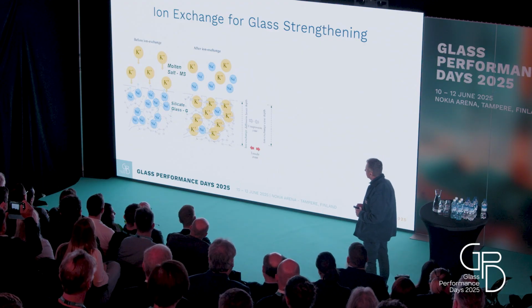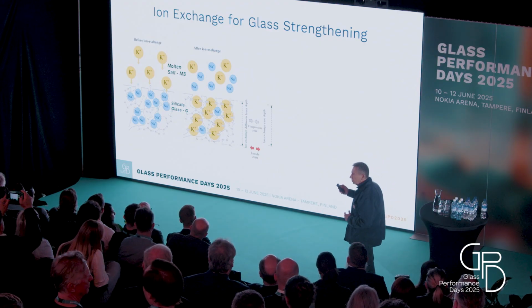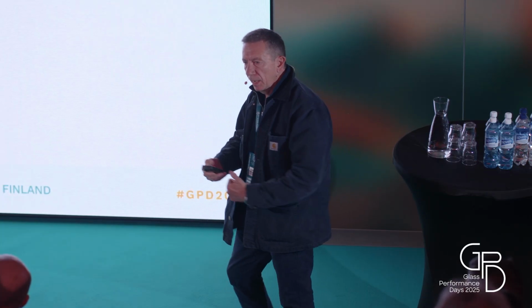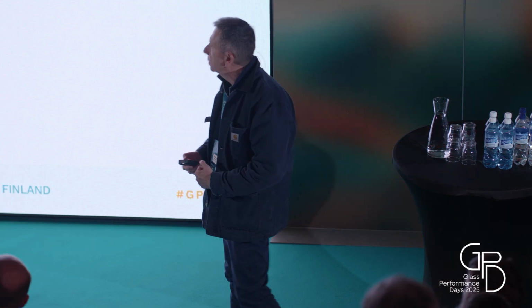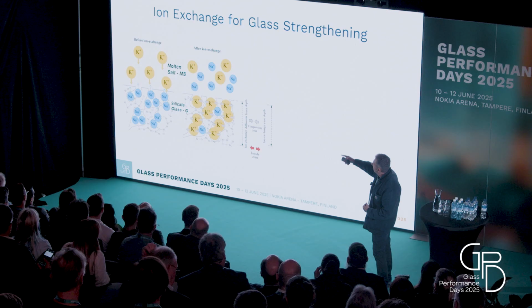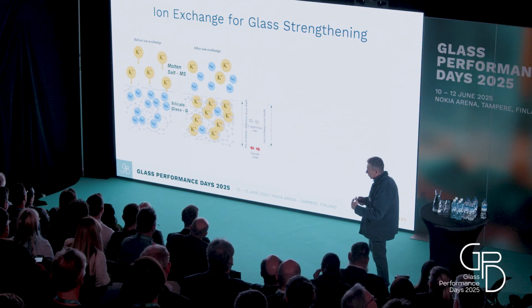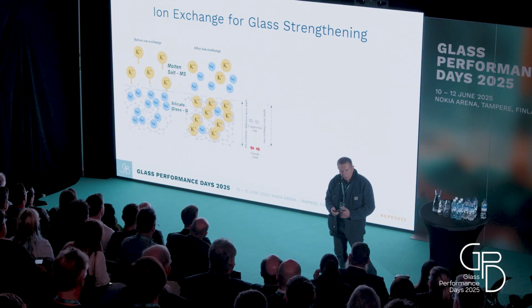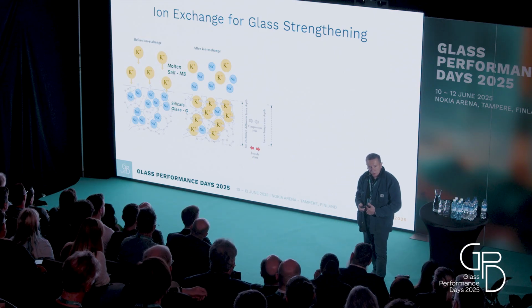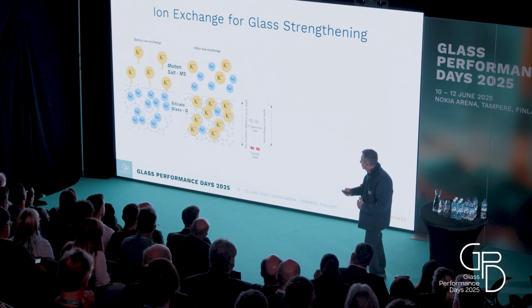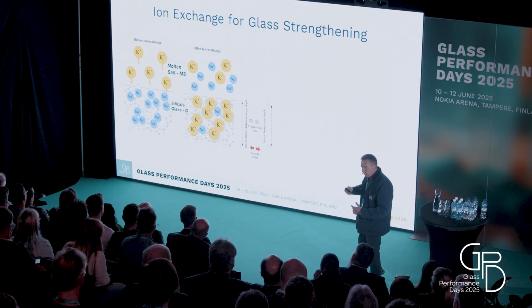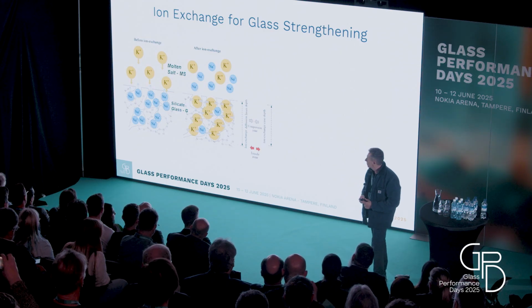In this case, it is potassium nitrate. Because it's molten, KNO3 is separated into K+ and NO3−. And then you have the exchange, which is driven by a gradient in the electrochemical potentials of the two ions, sodium and potassium, in the respective mediums.